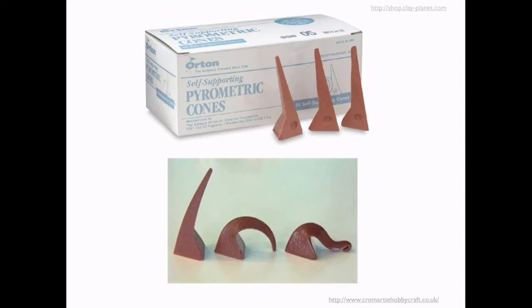And so that's what we use pyrometric cones for. So it's measuring what the fire has done. And so what these are is they're materials that have been engineered so that they will melt and start to bend when they've absorbed a certain amount of heat work. And so that lets you tell how far into the process you've gone. You can't really stick a fork in a baked potato. You could stick a fork in a baked potato, but you can't do anything like that to your ceramics that are in your kiln. So that's what the cones are for, to have a visual representation of how far things have progressed.